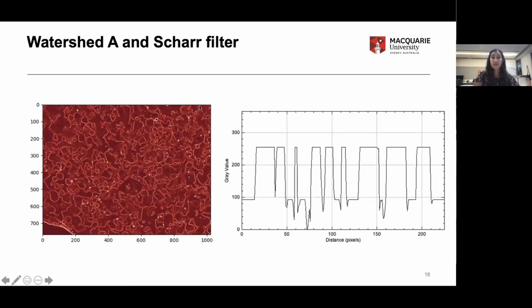We make use of 2 watershed algorithms to help us actually analyze and pick out grains. The first watershed algorithm works in combination with something called a Scharr filter. A Scharr filter is essentially outlining all the grains that we can see. And the reason it can identify these grains is because the grayscale value of a grain interior is very high. As we fall away to the edge of the grain, the grayscale intensity drops because we hit that dark background. And that's what you can see here. So these peaks here are the middle of grains. Where we have these dips, that's where we're starting to see those grain boundaries. So the Scharr filter does a really good job at highlighting everywhere we see these contrasts in the grayscale imaging. And that's thanks to that improvement of the smoothing filter we applied earlier.